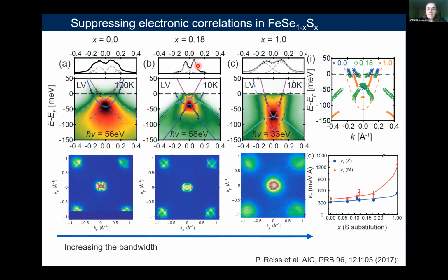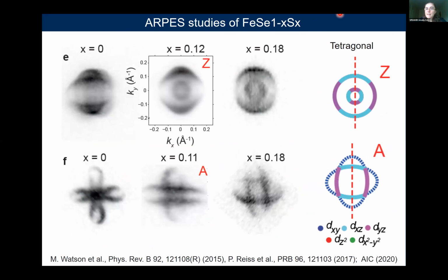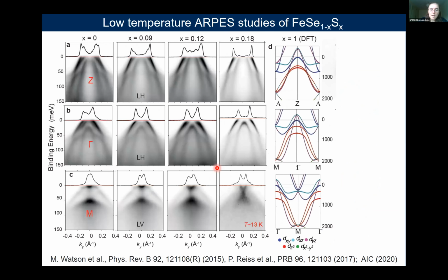Now here, I mean, this is probably the best way to think about what happens in sulfur substitution. This is the 18% sample, which is just outside the nematic phase, so it's in the tetragonal phase, and you do have the two ellipses, exactly what you expect to have in the tetragonal phase. So obviously, the ends of these two ellipses are the DXY parts. So you see the position, this is where the shoulder is for the DXY band. It's much harder to see, but that's what you expect those positions to be.